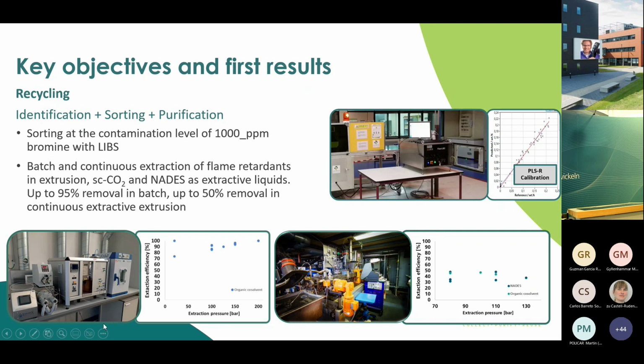Next step, since this is of course a batch reaction, and this is the picture you see on the right, is shifting to a continuous extraction method, and therefore we are using a twin screw compounder. And in the twin screw compounder, we again add the supercritical CO2 and our co-solvents.